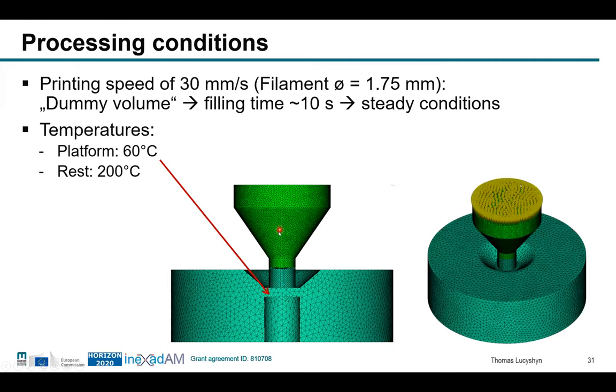So basically the flow along here until here is interesting for us. It mimics the real situation. And what is around here is just for some space where the melt can go somewhere, so that we have some continuous filling time of 10 seconds where the material is flowing through here, and maybe some conditions can change during this continuous flow. The platform here was set to 60 degrees, which is similar to 3D printing, and the rest was set to 200 degrees. So this is the flow path where the melt is flowing, and the platform was set to 60 degrees C.